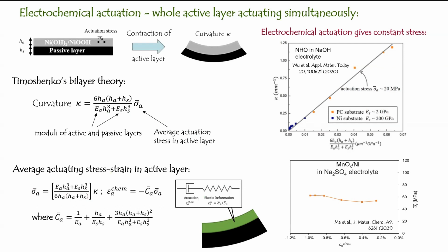Of course, if you have a bigger actuating stress in the active layer, the more should be the actuating curvature. So experimentally, you can do the reverse. You can measure the curvature experimentally, and then you know this factor, then you can work out the actuating stress. You just reverse that equation. You can also make use of other equations in that theory to work out the actuating strain. The system is like a dashpot connected in series with elastic resistance, because if the top layer shrinks, it's like you have a dashpot shrinking, right? You have some shrinkage, but then because of the elasticity in the entire system, you have some elastic resistance. So the relation between the stress and the strain is via this equation.